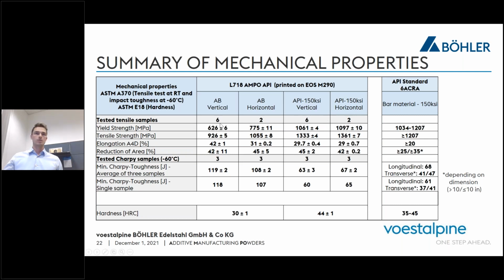And of course, you need to consider that this is in megapascals and not in KSI. But basically, 150 KSI is 1034 megapascals. So we are well into the 150 KSI range. So we achieved the yield strength and also the tensile strength, with the elongation and reduction of area well into it too. And then if you go to the Charpy tests, you can see that we achieve high toughness as well.